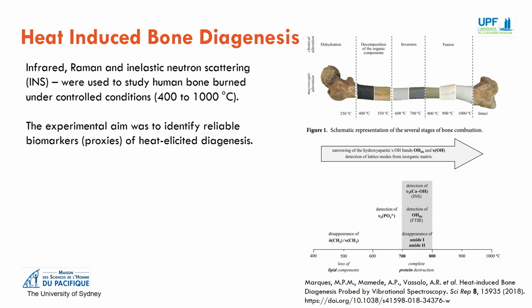The research undertaken by Marques and colleagues determined that the most significant spectral differences were observed between 700 and 800 degrees Celsius and included degradation of the organic protein component, as well as the presence of new bands attributable to the inorganic matrix, as seen in the schematic representation in the figure on the bottom right-hand side of this slide.